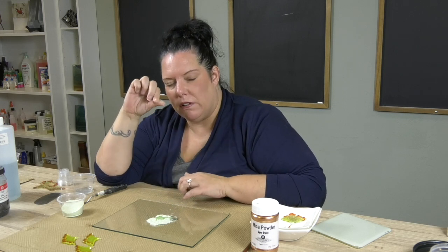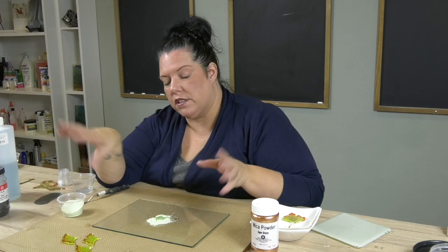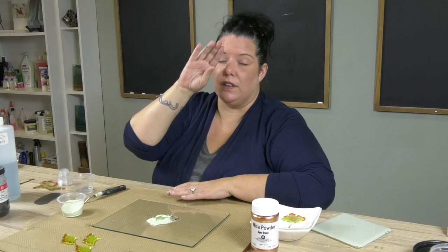If you want this powder to be stiff, if you make the powder too liquidy, it's going to melt. When you put it in the kiln, the whole thing is going to collapse like melted icing, okay? We have to find a thick paste. Now here is the best trick I figured out. This took me 2 days to figure out how to explain this to you guys, because